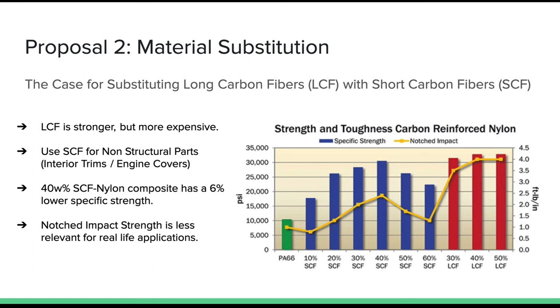However, this should not present a real problem because failure by impact can be split into two separate processes. We have crack formation and then crack propagation. However, real-life parts would not ideally contain cracks or notches, thereby making these parameters a little bit irrelevant. Manufacturers should be able to safely use a vastly cheaper SCF in the presence of a stringent quality control program. This, however, would require detailed research and development study by automakers.